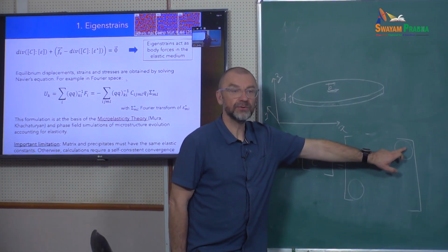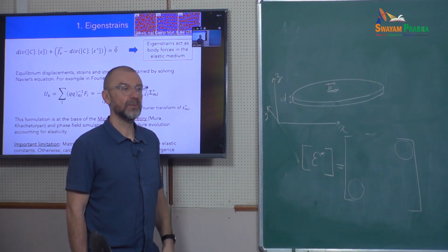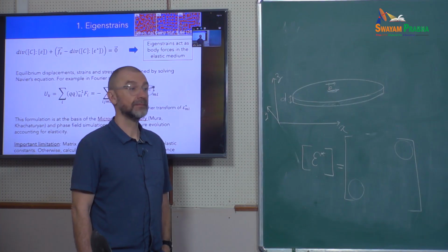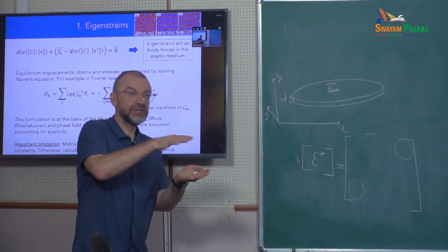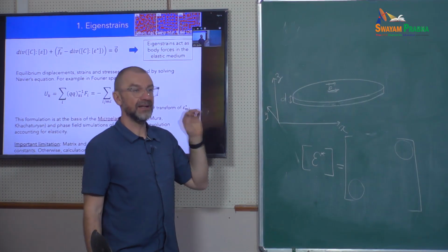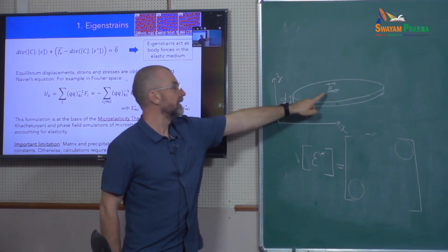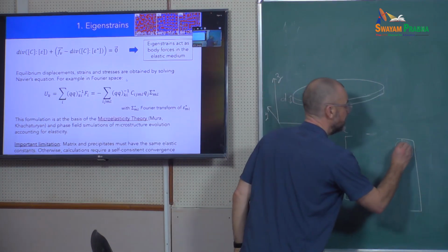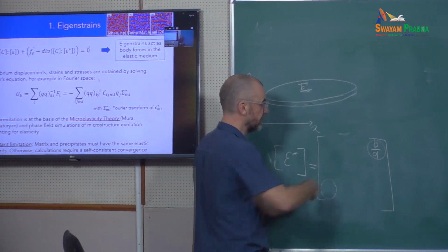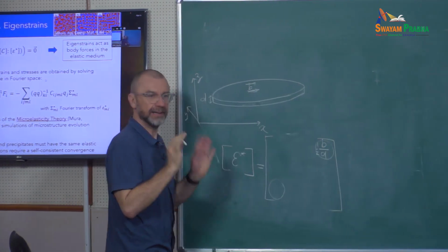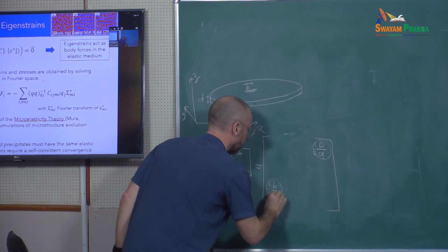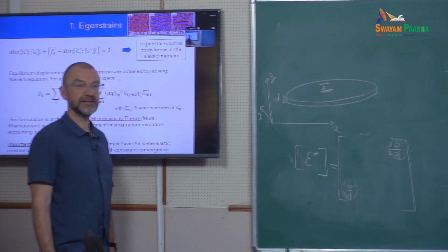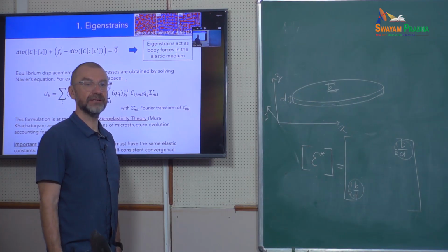What will this term be equal to? What shear would that be? It's the relative displacement. So you move by B over a distance D. So this is B over D. And because of the symmetry business, there's a 1/2. And then you have a 1/2 here, and you have a B over D here. You see what I mean?